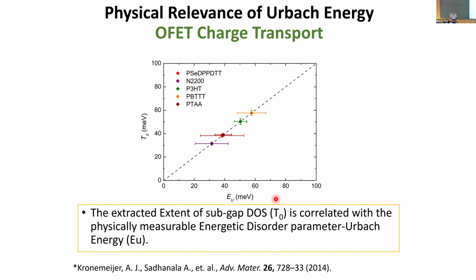And with FETs, you basically do a lot of painful work to measure the subband gap density of states. This was one of my first papers ever. What we did here is measure FETs using all these organic semiconductors, and measuring FETs at various temperatures takes months, not days. We did the same films with optical measurements in just a few hours.